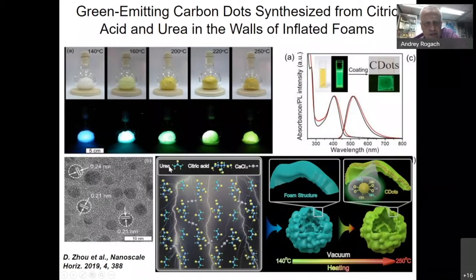because when we mix urea and citric acid with calcium chloride, calcium chloride here is a kind of foam making material. So we put them under vacuum and then we heat them up under vacuum at different temperatures, and we form these light emitting foams. It's like a powder, foam-like structure, and you see the color of emission is different. And if we take a piece of this powder and put it on a TEM grid, we can find carbon dot nanoparticles.